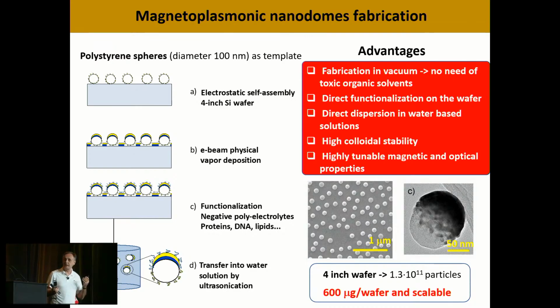So as I told you, we buy our polystyrene beads of 100 nanometers, and then we electrostatically self-assemble them on a surface. Usually we use silicon, but we've tried other types of substrates. Here is how it looks when they are assembled on a surface. And then, using electron beam evaporation, we evaporate the two layers, the iron and the gold, on top. And then, if necessary, we can functionalize the nanoparticles as they are on the wafer. And finally, using ultrasound, we release the particles from the substrate, and we can transfer them to water very easily.